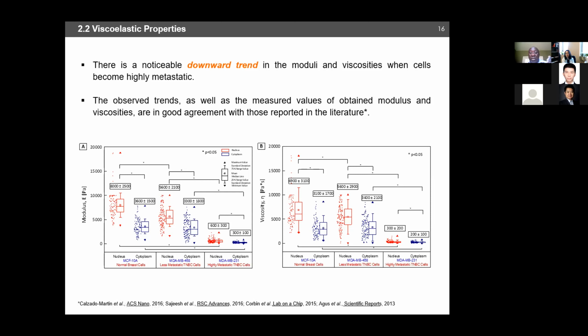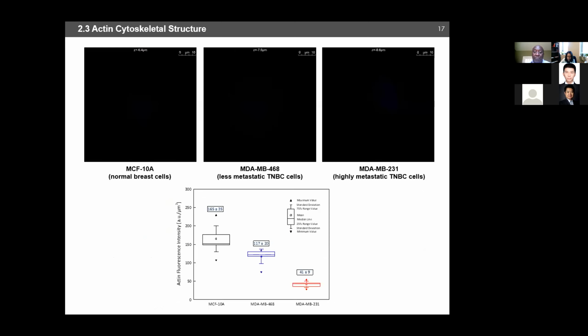So basically the moduli reduce with increasing metastasis of the cells. And the same is true for the viscosities. The viscosity is also reduced as the cells become more metastatic. So what this basically shows then is that the moduli and the viscosities can be used as mechanical biomarkers of the progression of the tumor from no tumor to less metastatic to more metastatic.